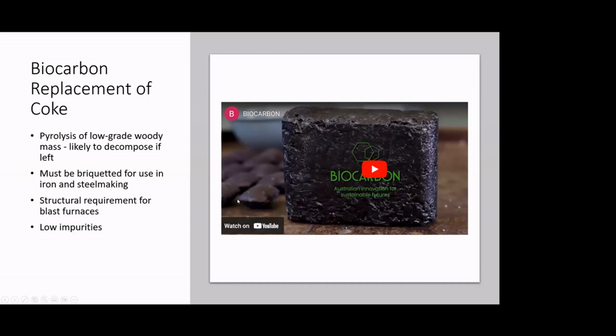So one of the other options was to replace the coke with a biocarbon, which in my opinion is not really low carbon emissions, in that you have to rely on growing that forest, and it's a bit of an accounting thing rather than an actual transition away from carbon-based steelmaking. This is something that's being trialled in Australia, and initially Carbonscape were interested but have pivoted to battery graphite. It's basically a pyrolysis of woody waste, and it's briquetted and used in the blast furnaces. The advantage is it doesn't have many impurities, but I don't know whether we'd have enough woody waste. If we look at Gisborne, maybe we have plenty of woody waste for this sort of thing, but it's not going to last in the long term.